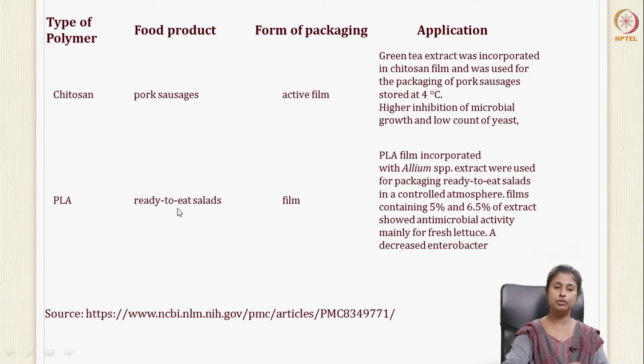Similarly, PLA was used in ready-to-eat salads as a film. This PLA was incorporated with allium species extract, that is garlic extract. It was used for packaging ready-to-eat salads in a controlled atmosphere. The films that contain 5% and 6.5% of this extract showed antimicrobial activity, mainly for fresh lettuce, and a decrease in Enterobacter.